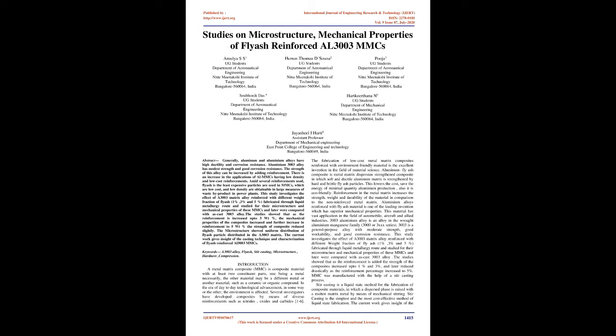1%, 3% and 5%, fabricated through the liquid metallurgy route and studied for the microstructure and mechanical properties of these MMCs, and later compared with as-cast 3003 alloy. The studies showed that as the reinforcement is increased up to 3 Wt%, the mechanical properties of the composites increased, and with a further increase in reinforcement to 5 Wt%, the strength of the composite reduced slightly.